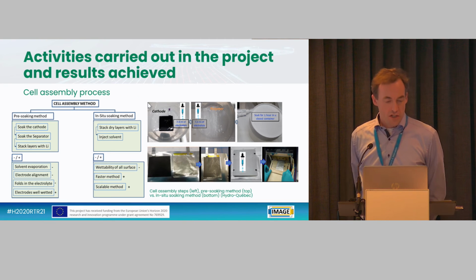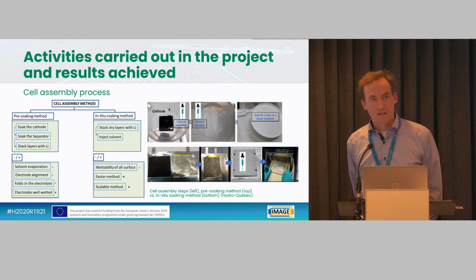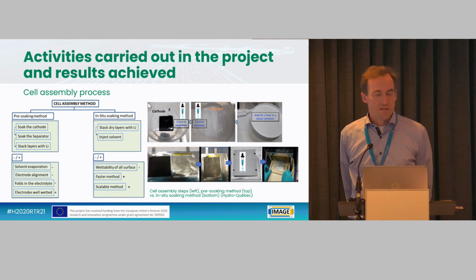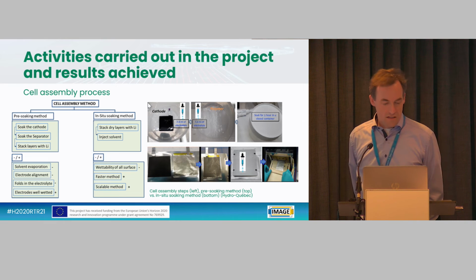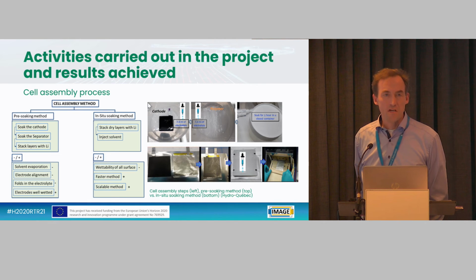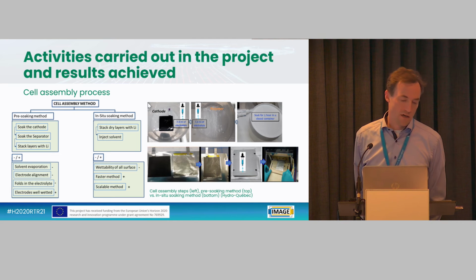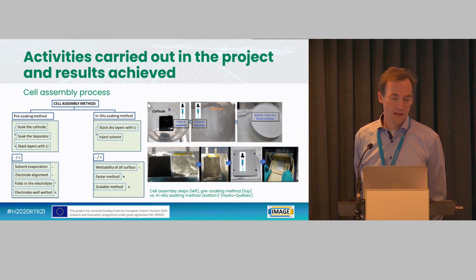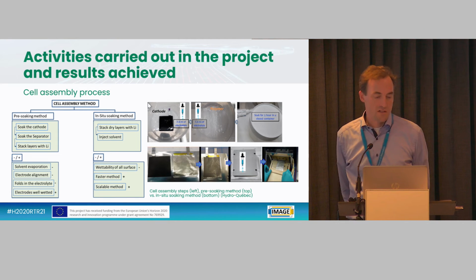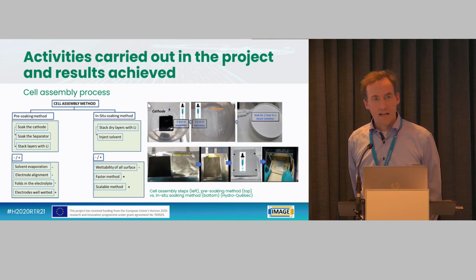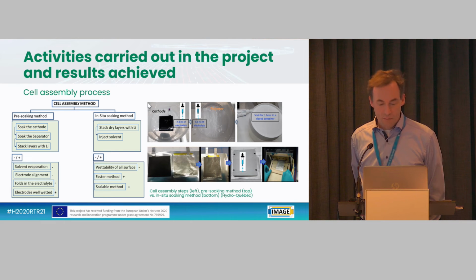The next step was to bring together these materials and to start building up cells. For cell assembly, there are basically 2 ways we found out. It's either you take the components, which is cathode and separator, and bring them together with some electrolyte, let it soak from the outside. Under very controlled conditions, the soaking is very good, but the handling afterwards is very problematic.